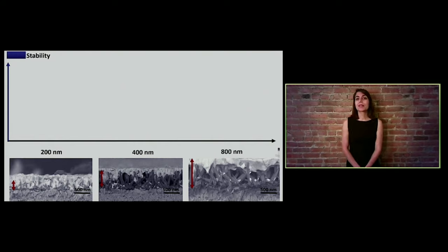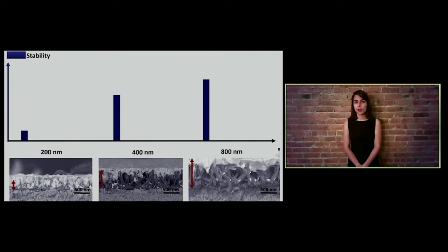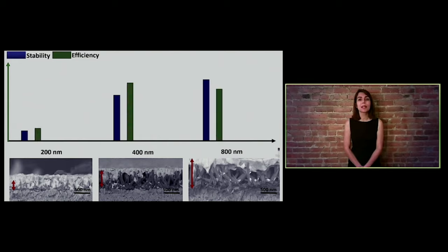What I discovered was that the stability of perovskite solar cells based on longer nanorods tends to be higher, which is encouraging. I also measured the efficiency and realized that it does not necessarily follow the same trend as stability. But my research can help us with understanding that.